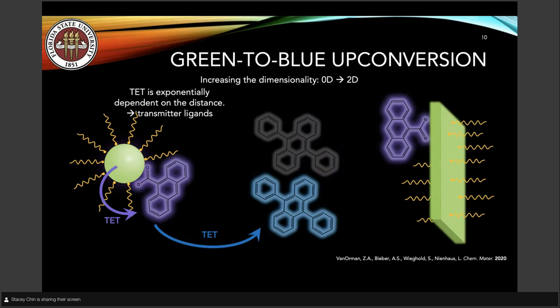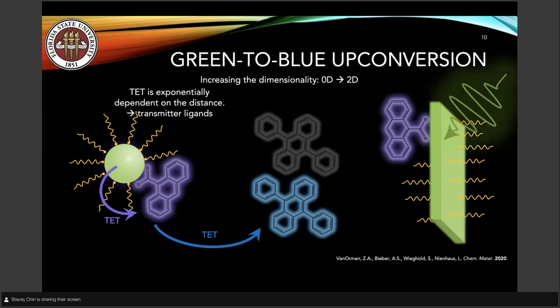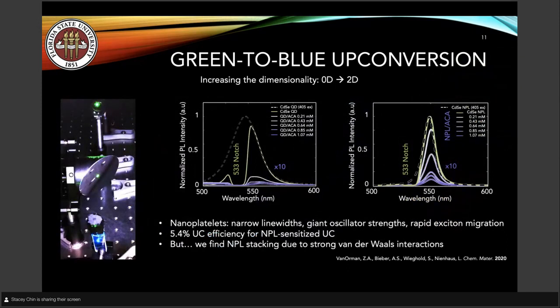Okay, so we were now interested in moving from the zero-dimensional quantum dots, so spherical quantum dots, to two-dimensional nanoplatelets, and using them as sensitizers. Next slide. In particular, we were interested in using them due to the fact that there is no energetic polydispersity in nanoplatelets, so therefore they have narrow line widths. They have giant oscillator strengths, and it's been shown that you can have rapid exciton migration in films or aggregates of these platelets, and we thought this could be fairly interesting to look at.